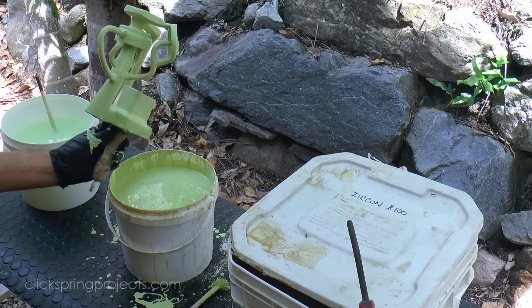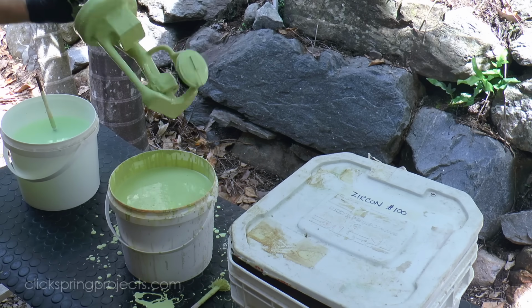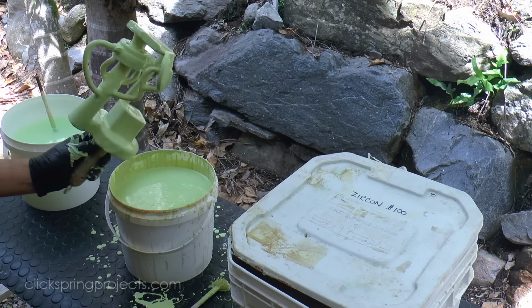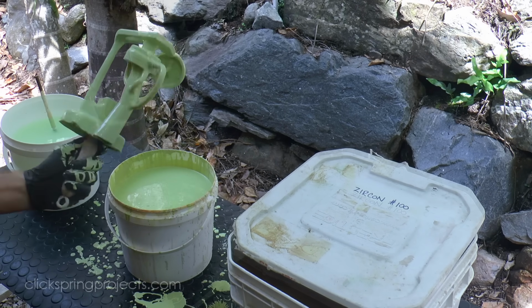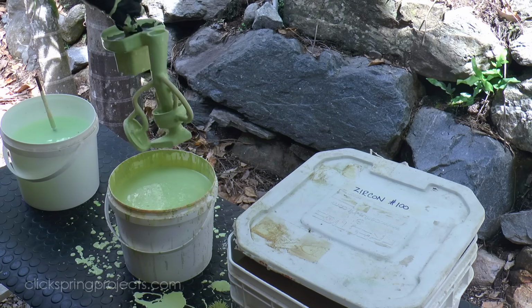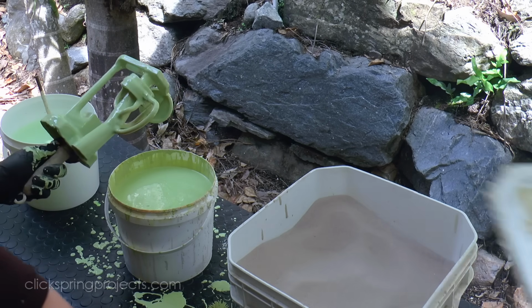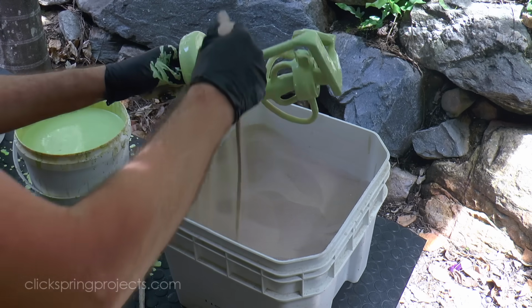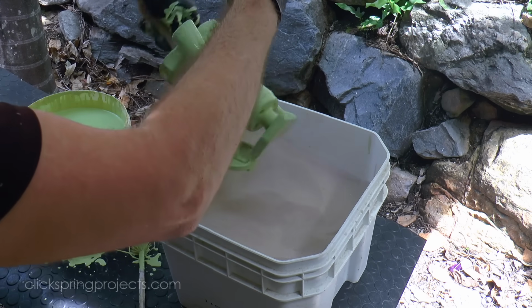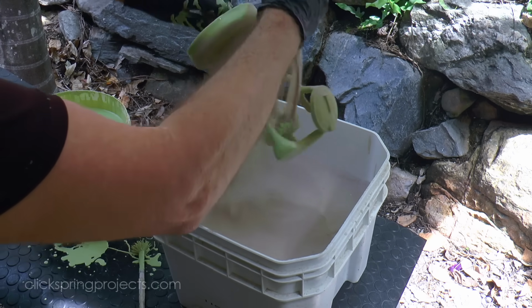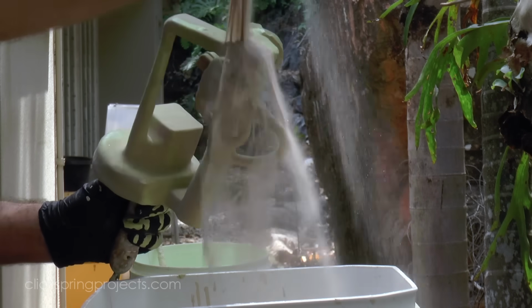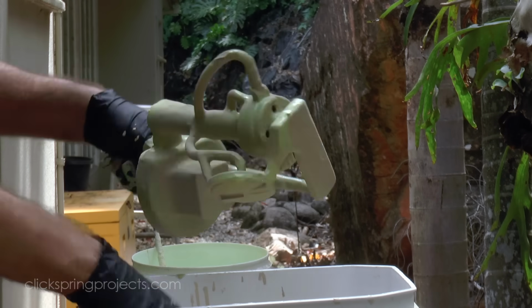Occasional soft bursts with compressed air helps to remove the bubbles too. Then, as best as possible, the pattern is kept in continuous motion as the excess slurry drips off and back into the bucket. Once the drips have mostly stopped, the sand is then added by hand, again keeping the model moving to minimise the tendency for the slurry to drip or fold over upon itself as the sand is being added.